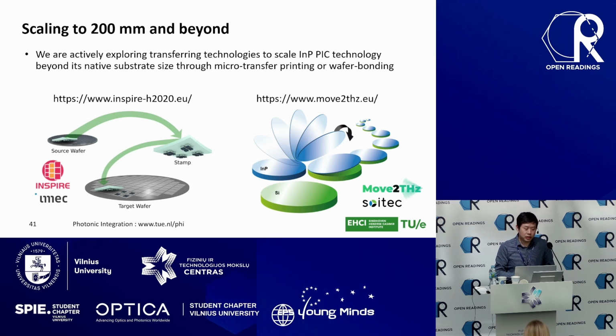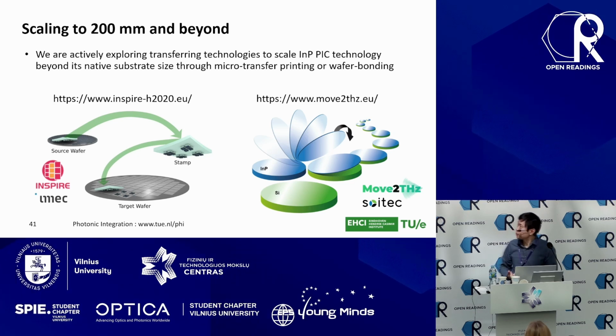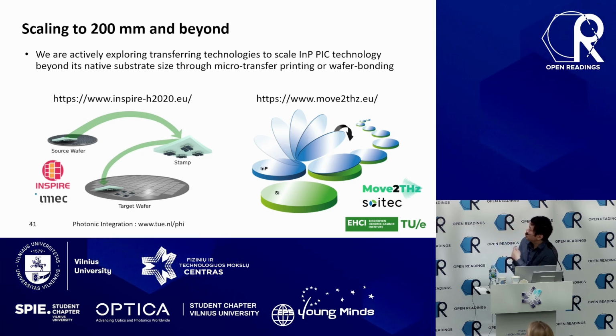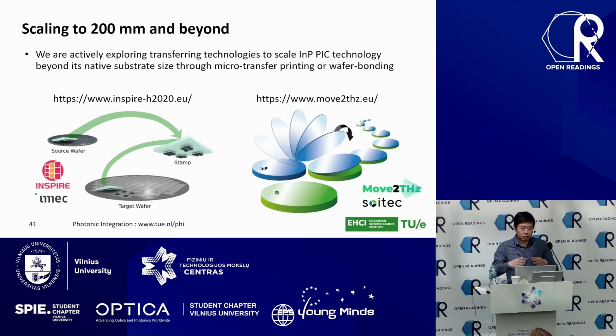So we are actually looking at technologies for how to go beyond the wafer size limitation for indium phosphide. Yeah, I give you 2 examples of the running projects we are working on. With IMEC, we are working on microtransfer printing. So we will produce the indium phosphide membrane devices in their source wafer, 3 inch, 4 inch, 6 inch, doesn't matter. But then we can transfer them onto a much larger silicon wafer, 200 millimeter, 300 millimeter, by pick and place, where we can pick small pieces of indium phosphide and populate them onto silicon substrates.